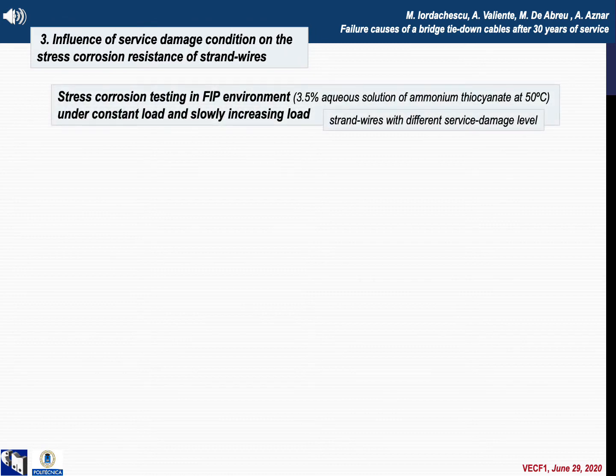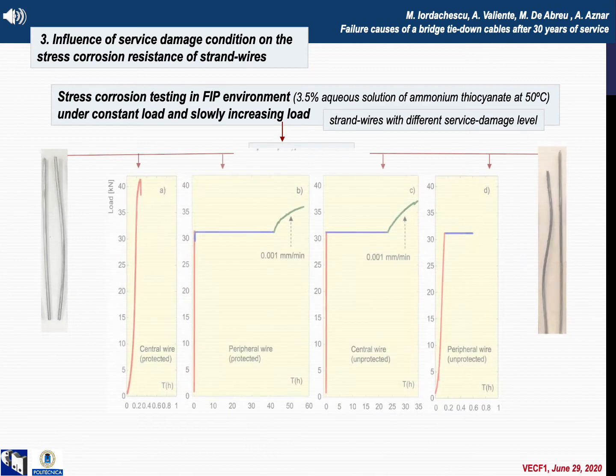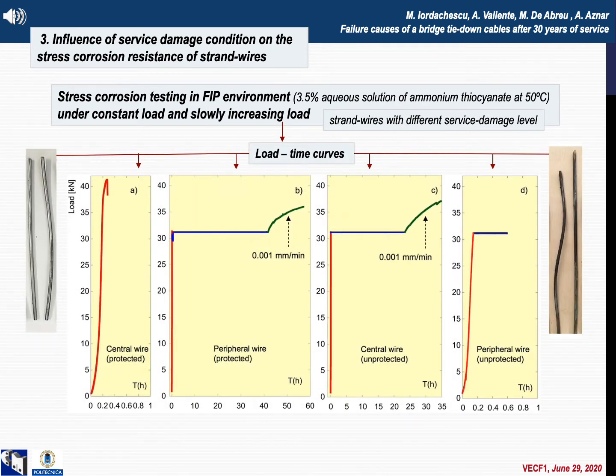In this work, 3 wire samples extracted from the broken strand of one of the bridge piles have been stress corrosion tested in FIP environment. 2 of them came from peripheral wires of the strand sections, respectively protected and unprotected by the polyethylene sheet, and the third an unprotected central wire. Thus, the last two wire samples had been permanently subjected to the pile's interior environment, but the central wire sample had the additional protection offered by the other 6 peripheral wires of the strand.